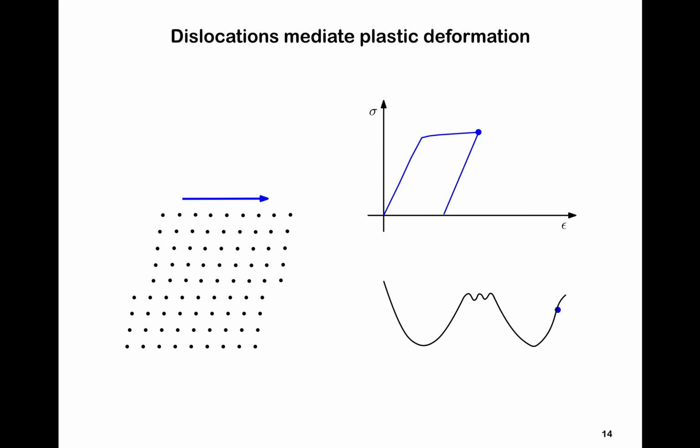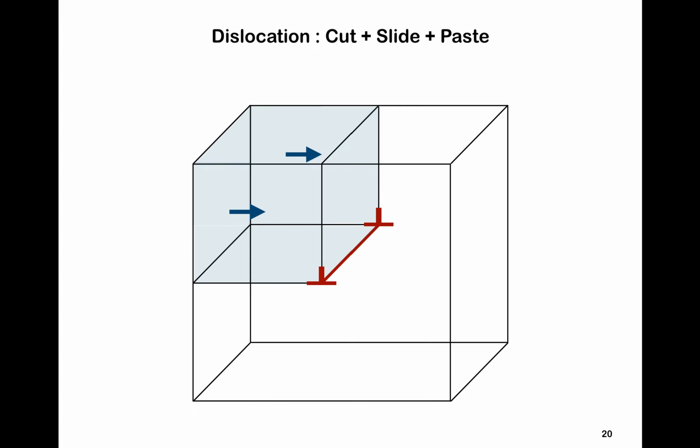Okay, except now that we are not cutting all the way through, we are only cutting through part of the crystal. So where does that cut half end? It ends on this particular line, right? So you're cutting until that particular point, and that is where the slip ends. And that trace of that region, the geometric region, is what you call a dislocation line.